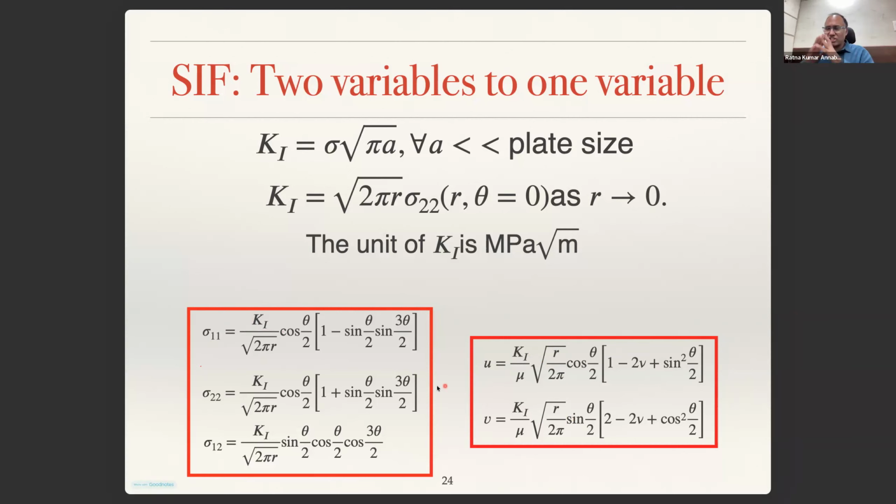This is a pure elasticity solution, which is only of mathematical interest, because in reality, you will not have pure elasticity ahead of the crack tip. As soon as you apply some force, immediately plasticity develops.